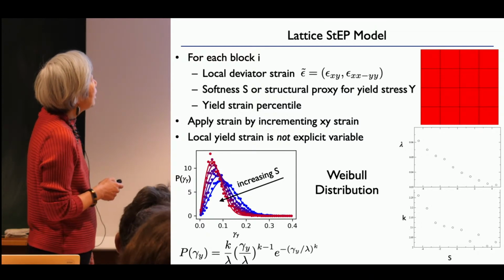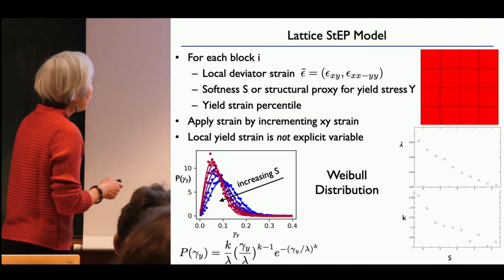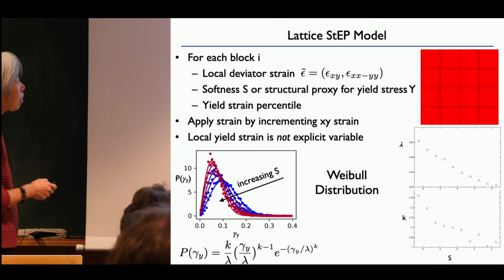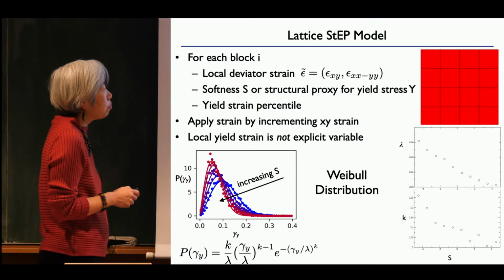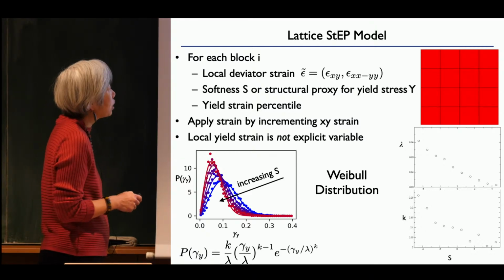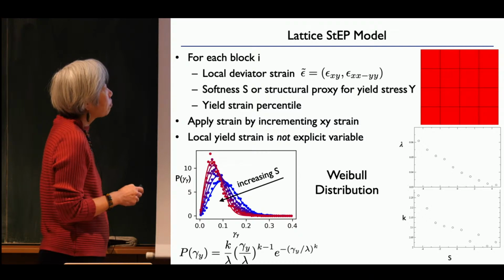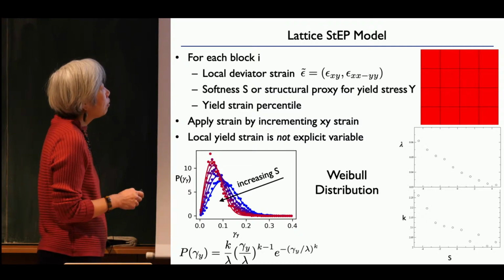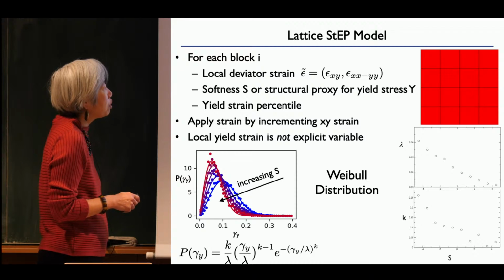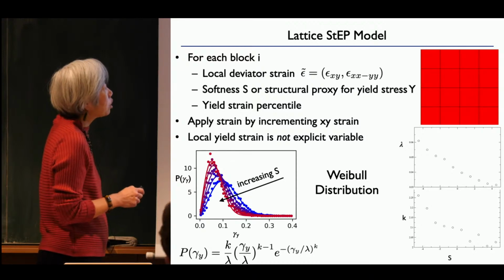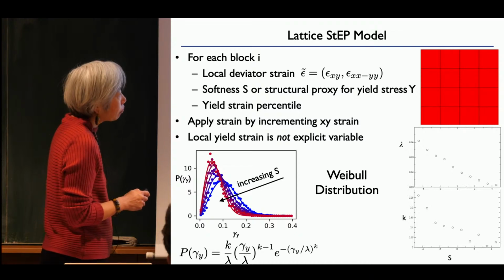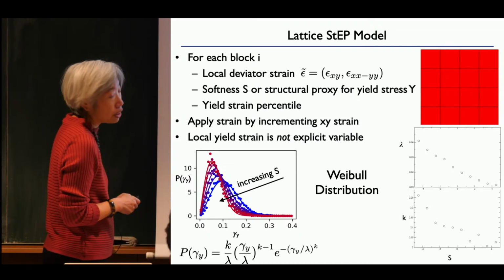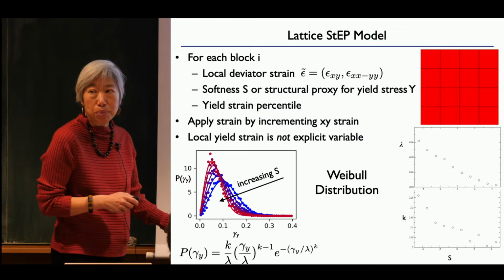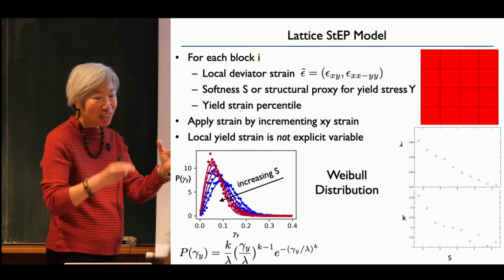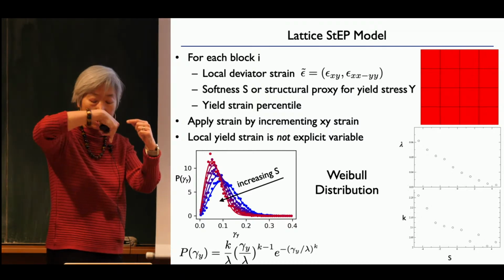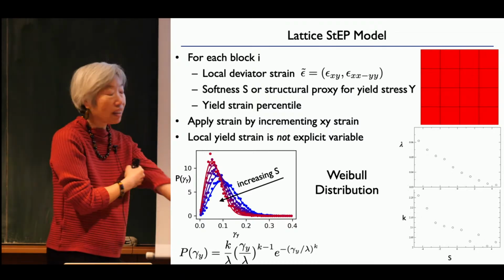So each block has a softness, and each block has a yield strain percentile. What do I mean by that? It turns out that if you look at particles of a given softness, there's a yield strain distribution corresponding to it. Particles of the highest softness have a yield strain distribution which has a lot of contributions at the low end, and a small median. These are fits to the Weibull distribution, which is an extreme value distribution, which is expected because the local yield strain is this: you always take the direction in which the yield strain is the lowest.